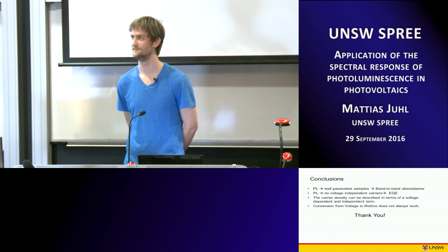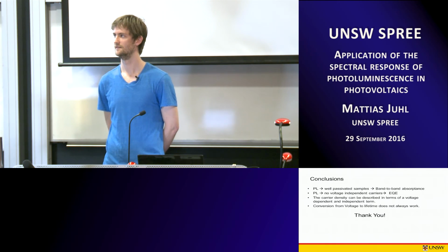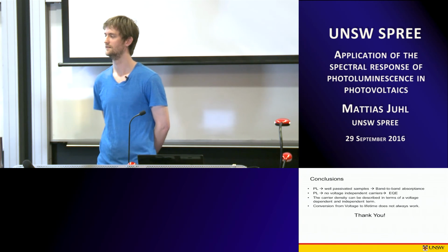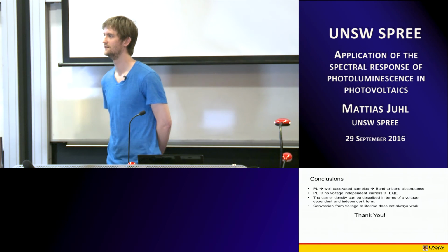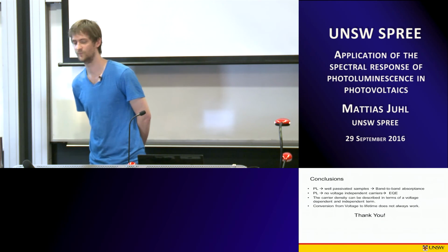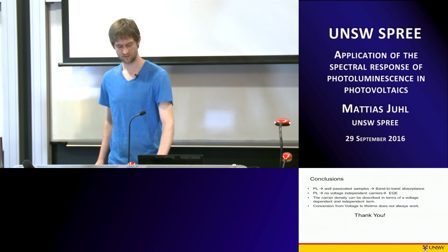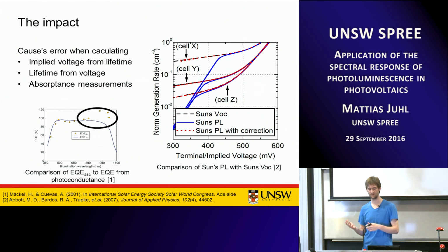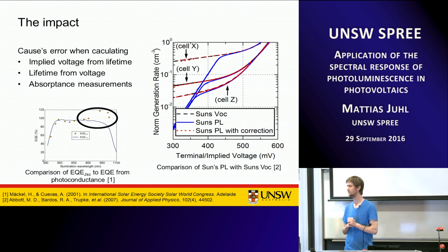Hannah: Very nice presentation, thank you. Question: if you have already created the link between lifetime and injection-independent carriers, can't you just measure the lifetime by measuring the independent carriers? Yes, you can. The real problem is, you need to know two things. You need to know the real EQE or the real absorptance to be able to figure out how many independent carriers there are. And with EQE, you can't really measure surface recombination velocities when they're getting below 1,000. It becomes really tricky. And it's roughly the same for this big hump.